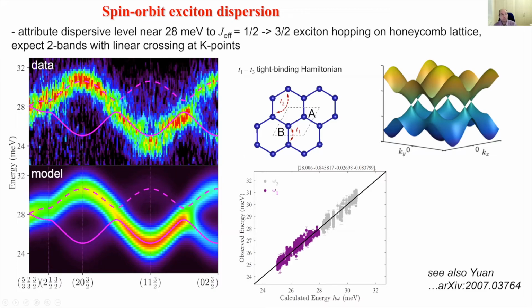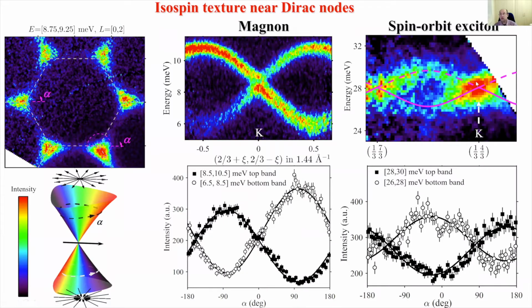And the dispersion relations that we extract experimentally could be well parameterized theoretically, and also the intensities. And this explains why most of the places carry intensity just for one mode, but there are regions with intensity in both modes, as we see experimentally. So we can also look for evidence of narrowing of the spectrum close to the corners of the Brillouin zone. And indeed, the resolution here is not as good as at the low energies, but still there's very clear narrowing and